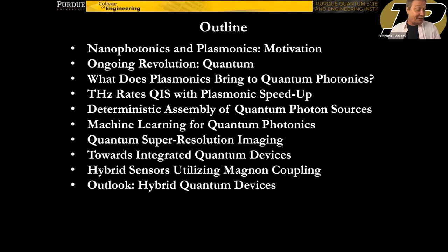Yeah, that's a good question. You see, plasmonics was the field which was almost exclusively developed based on two materials, silver and gold. And that's simply because the decay rate is relatively small there, losses not as high as in other materials, but they have plenty of disadvantages. They cannot sustain high temperature, or even elevated temperature. If you have a nanostructure made of gold, even if you increase the temperature up to several hundred Celsius, which is way below the bulk melting temperature, because of sintering you start to change the shape, and your antenna actually goes off resonance. So in that regard, the refractory plasmonic materials, as mentioned by the person who asked this question, are actually very promising,